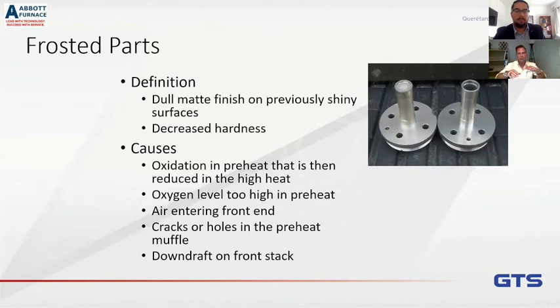So now the surface isn't as smooth. And when it goes into the high heat where you have that hydrogen doing its work, it reduces that oxide, but it creates little cavities or little bumps wherever the oxygen was. And now it reflects light differently than something that did not oxidize. So that's why you get this dull appearance, okay?